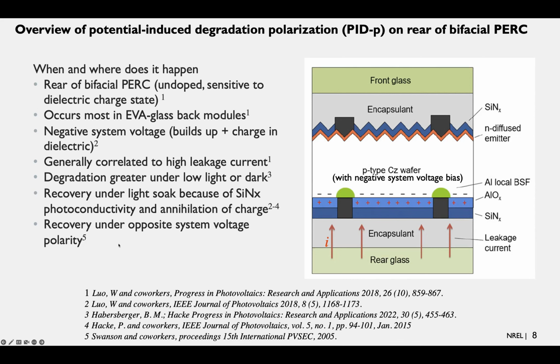And finally, recovery under opposite system voltage polarity occurs. So here we have degradation with the cell under negative bias, and that negative bias would attract the positive charge to the dielectric here, leading to the PID polarization. But if we were to reverse the bias on the cell, we drive away that positive charge back out towards the glass, and the PID polarization we saw would recover. So that's kind of a primer on PID polarization to explain what it is we see in the next slides.